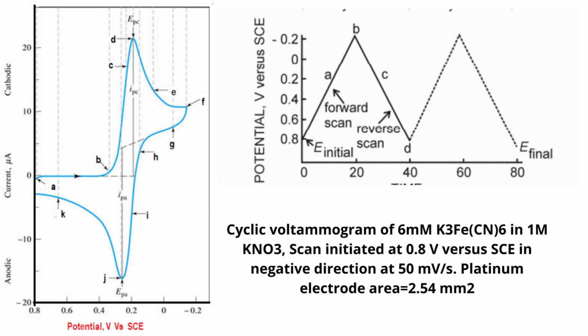Cathodic current is indicated by B due to the electrode process, ferricyanide to ferrocyanide. The cathodic current increases rapidly, B to D, until the concentration of ferricyanide at the electrode surface is substantially diminished, resulting in the current peaking at D. The current then decays, D to G, as the solution surrounding the electrode is depleted of ferricyanide due to electrolytic conversion to ferrocyanide. The scan direction is then switched to positive at minus 0.15 volt for the reverse scan.